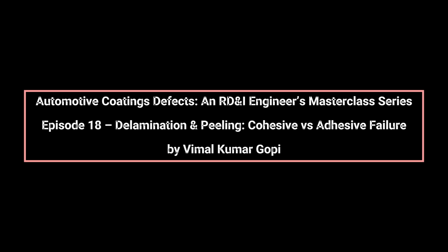Excessive thickness increases internal stress during solvent evaporation and cure shrinkage. Thick films also experience greater thermal expansion mismatch between layers, especially in multi-layer systems. Thin films may lack mechanical integrity, promoting cohesive tearing under stress. OEM plants tightly control DFT not only for appearance, but for stress balance across layers, particularly near edges and sharp contours where peeling initiates first.